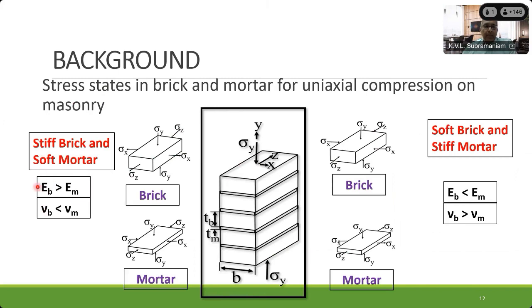So what happens? The modulus of the brick is much larger than the modulus of the mortar, and the Poisson's ratio of the brick is actually smaller than the Poisson's ratio of the mortar, right? So basically, brick is much stiffer material. When you apply a compressive stress on it, it doesn't expand as much laterally compared to mortar. Now, what happens in that case? When I apply an axial compression on the masonry, the brick does not want to expand as much. Whereas if you apply a compressive stress on the mortar, the compressive stress is the same in both materials, and because the Poisson's ratio of the mortar is much higher, the mortar wants to expand more.